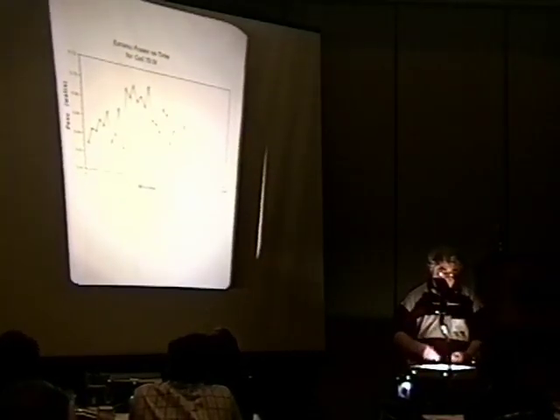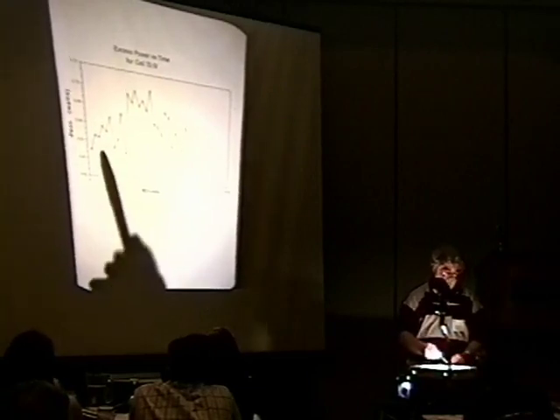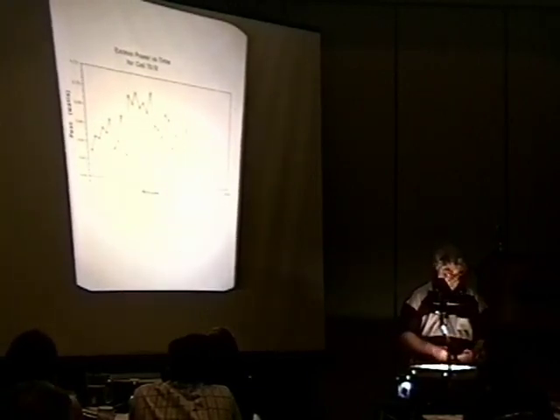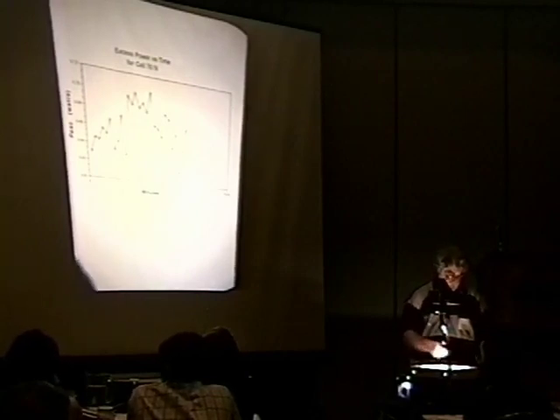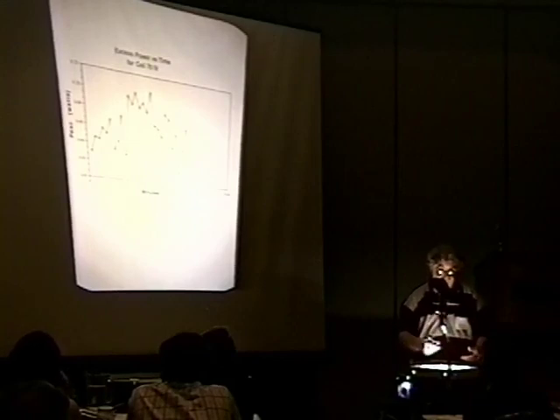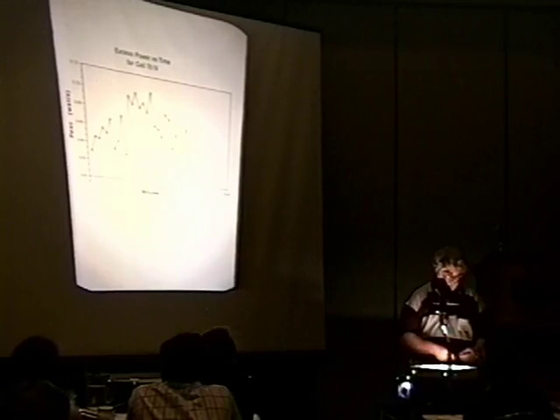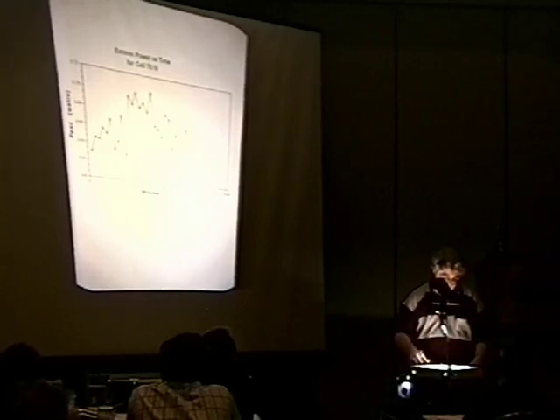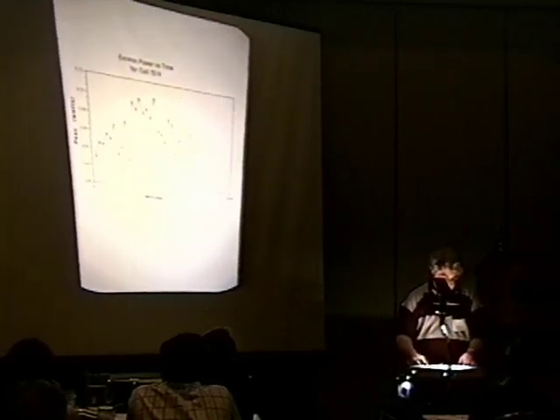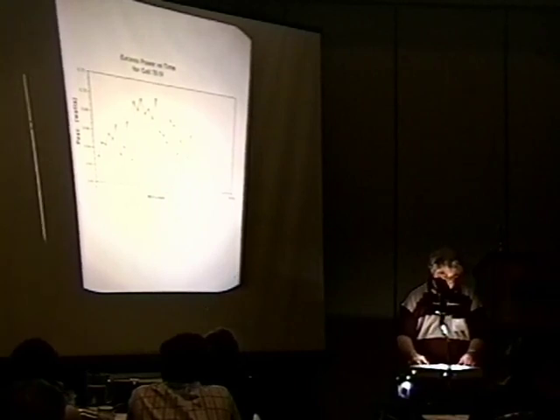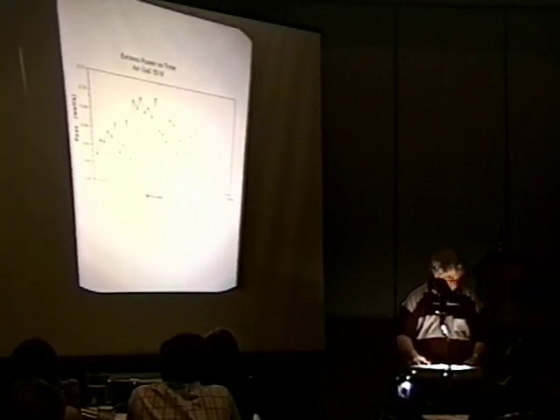And finally, when we make the averaging like 50 minutes a piece type thing, and now you definitely see sort of a heat burst. So what appeared to be bursty on a small scale is, as you go to higher scales, still bursty, and this is very much in consonance with the chaotic aspect that I predicted earlier, and that Srinivasan, in fact, indicated in his letter, which accompanied his very nice summary and review paper of cold fusion results.